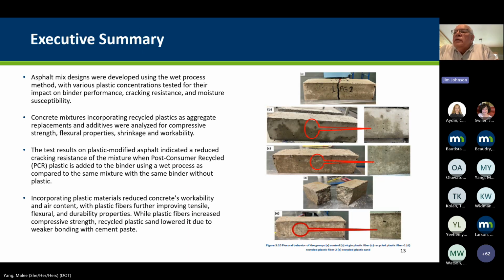The executive summary, as you know, is up front, but I wanted to use it as a conclusion to provide a little bit of oversight, going from the abstract, through the study, and what our findings and results were in a more concise process. As you see, let me read along with you on these. The asphalt mix designs were developed using the wet process method, with various plastic concentrations tested for their impact on binder performance, cracking resistance, and moisture susceptibility.